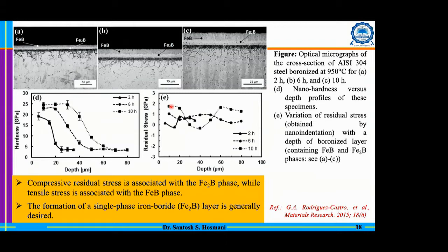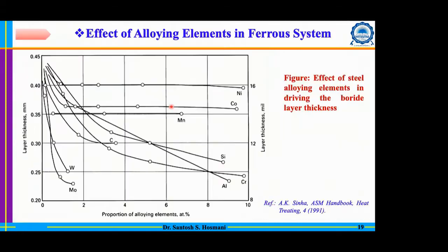Because whenever there is a formation of the Fe2B layer on the substrate, which will be ferritic or austenitic, during boronizing there is a lattice parameter difference. But Fe2B has some flexibility, and the elastic strain is sufficiently high there. Because of that, whatever the mismatch is, your system is able to accommodate it. So that's why very good adhesion of the Fe2B layer is observed, especially in the case of boronized steel.